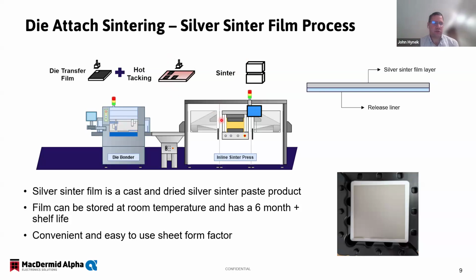If you wanted to, you could also put a silver sinter material on the top side of the die and sinter both the top side of the die and the die attach in the same step. That is something that we've tested out in our labs, and it works to great success. It has the potential to eliminate a step in the process. You can also see there's no drying step that needs to happen with the silver sinter film, because that's already done in the manufacture of the film itself. So the silver sinter film is a cast and dried silver sinter paste product.